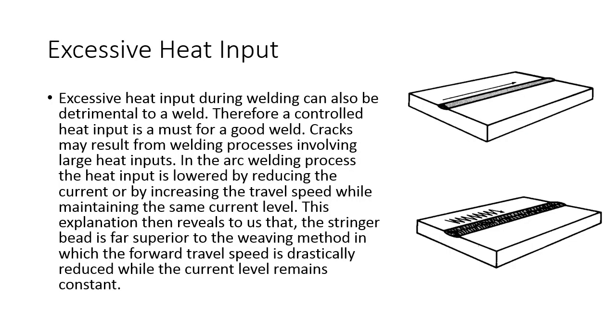Excessive heat input during welding can be detrimental to a weld. Therefore, controlled heat input is a must. In arc welding processes, heat input is lowered by reducing current or by increasing travel speed while maintaining the same current level. This reveals that the stringer bead is far superior to the weaving method in which forward travel is drastically reduced while current remains constant. Weave beads are bad, stringer beads are good.